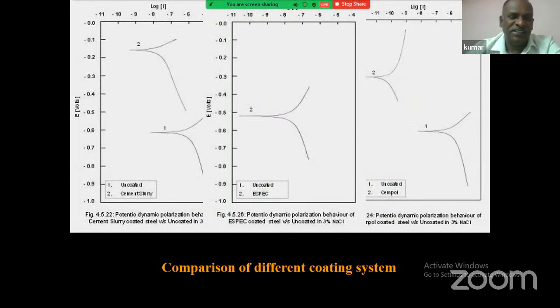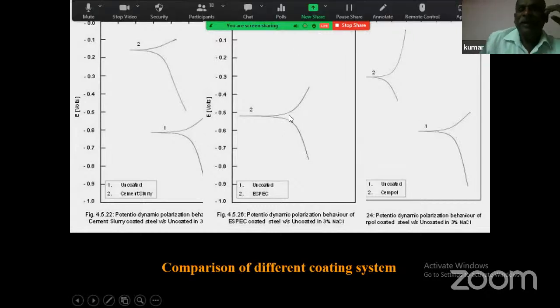So the mechanism you can just see here. These are the electrochemical analyses done. Number one, the first one is uncoated. This is the Tafel slope, which gives exactly the corrosion rate. The X-axis is the corrosion rate. When you see the cement, the corrosion rate is less, but the potential is very high, on the highly anodic side. When you are seeing epoxy, the potential is near to epoxy and the corrosion rate is also correspondingly less because it is a highly barrier type of coating.